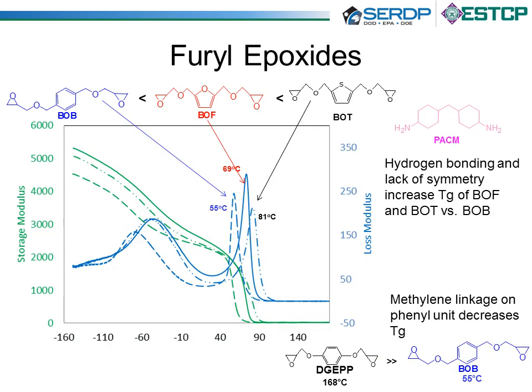We then also looked at furans to replace benzene-based rings in these high-performance materials. If we look at this, basically we have these diepoxy benzene rings, or this BOB structure, compared to this BOF structure, which is a diepoxy furan, and you can see that the diepoxy furan has a higher glass transition temperature, 69 degrees versus 55 degrees for the benzene-based one. And that's due to the lack of symmetry, as well as some hydrogen bonding associated with the furan ring. So using furans can actually be beneficial.